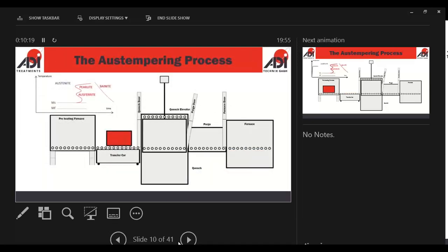So this is a small video of how the heat treatment works. With the heat treatment, it's obviously just a combination of temperatures and times. The first part we do is just to warm the castings up. This is not a stress relief. This is just to warm up the parts to sort of 600 degrees centigrade. It's really for cost benefits. It allows us to reduce the time that it takes to heat the parts when we put them into the furnace.